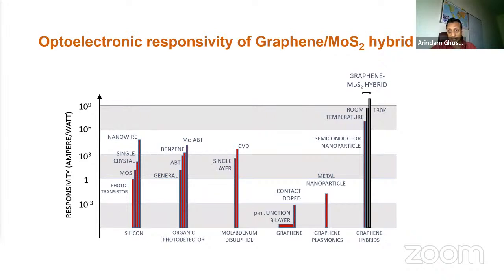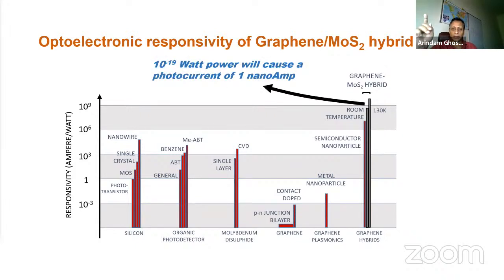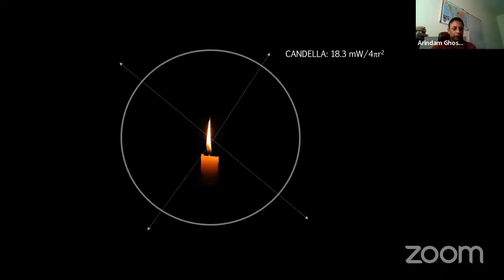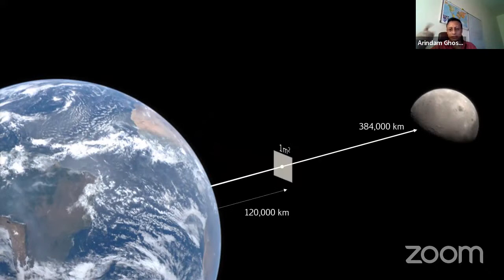This is about 10 to the power of 9 to 10 ampere per watt, which, if you can detect 1 nanoampere in your laboratory, leads to an energy sensitivity of nearly 10 to the power of minus 19 watt. So at 10 to the power of minus 19 watt, we produce a measurable 1 nanoampere of current. You know how much is 10 to the power of minus 19 watt? It's essentially a candle on the surface that can be detected 120,000 kilometers away with a 1 square meter area. So that is the amount of power that goes through at 10 to the power of minus 19 watt. It's an extremely sensitive photodetector that can be created.